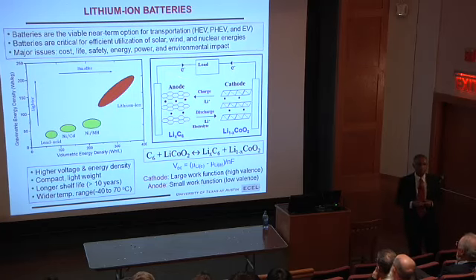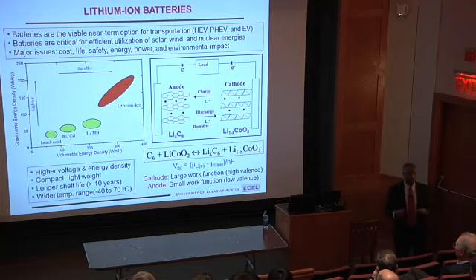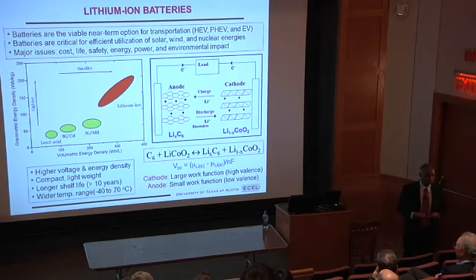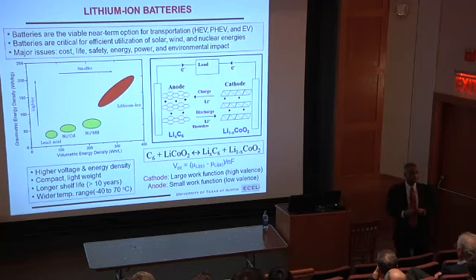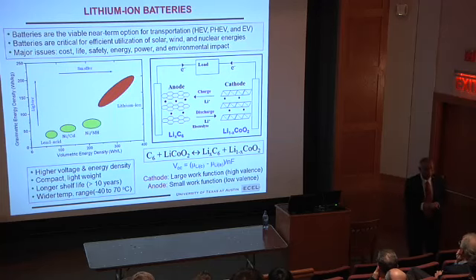It doesn't stop there. You want to have fast charge, fast discharge. If it is cell phone, laptop, slow, low power devices, I do not have to charge it in 5 minutes. It's slowly charging, that's okay. But if it is transportation or even grid storage, then you need fast charge, fast discharge. That depends upon 2 things. These materials should have fast lithium-ion conduction, lithium-ion diffusion from one lattice site to another lattice site. They should also have fast electronic conduction, both of them. If not, you will try to do some extrinsic stuff that will raise the cost. So that's the second. To have fast charge discharge rate, electronic and ionic conductivity is important.